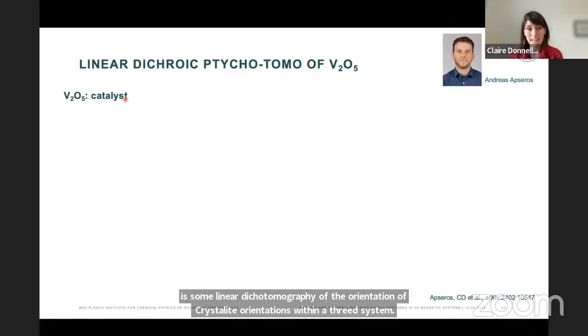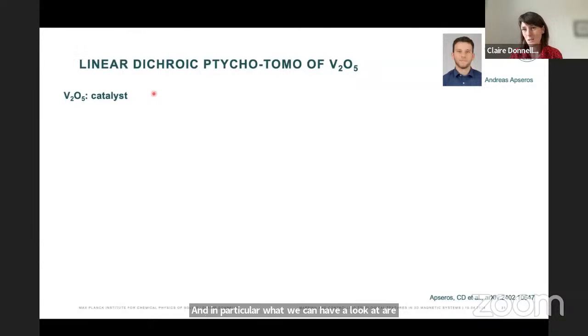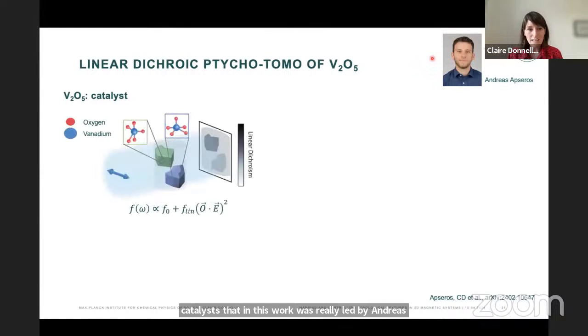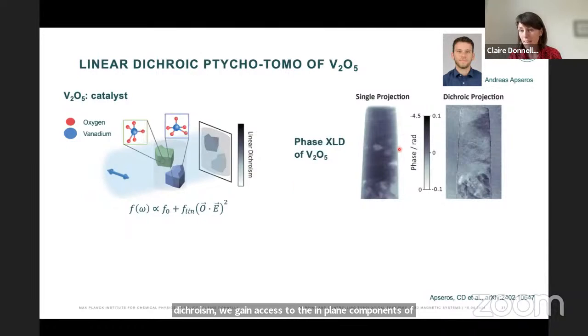In particular, we can have a look at these catalysts, and this work was really led by Andreas Apseros at the PSI, who's doing his PhD there. We have a catalyst of vanadium oxide, and similar to circular dichroism, when we perform linear dichroism, we gain access to the in-plane components of our orientation field. If we again perform phase X-ray linear dichroism imaging using ptychography, we can have a projection of the components of either the horizontal or the vertical orientation.